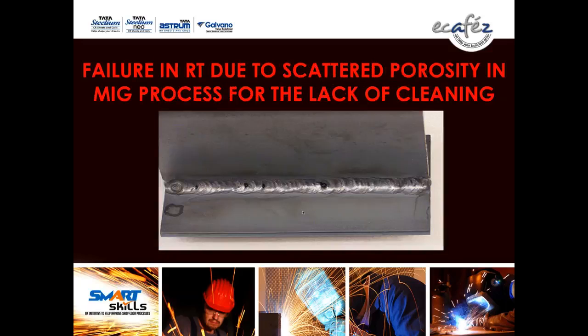Failure in radiographic testing due to scattered porosity in MIG process. This is for lack of cleaning. The joint which is done by MMAW root was not cleaned properly, and the rest of the rounds done by the MIG process were not cleaned properly. So the result is porosity in MIG process. See the pictorial view.